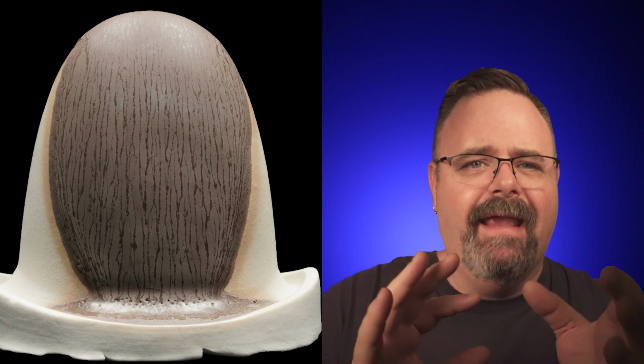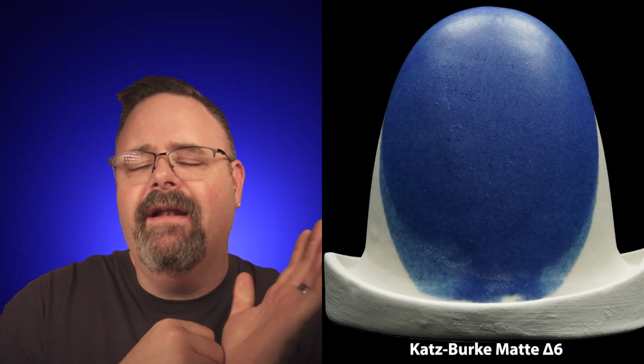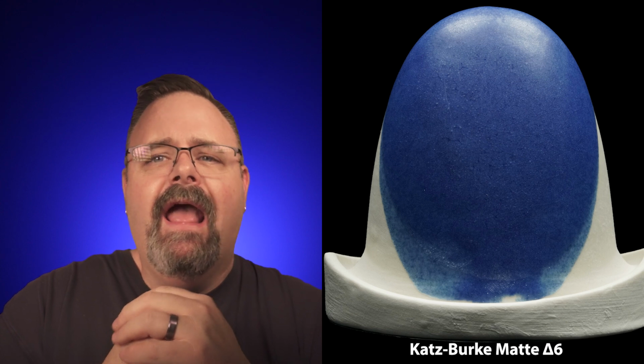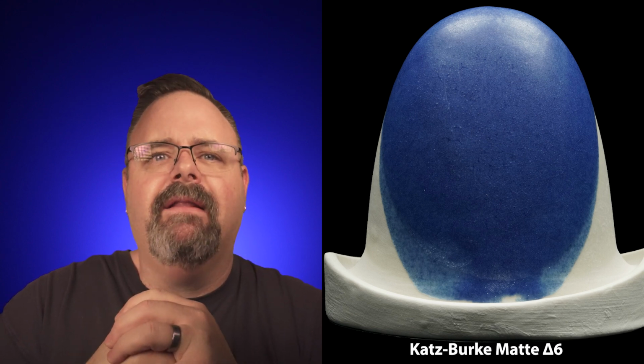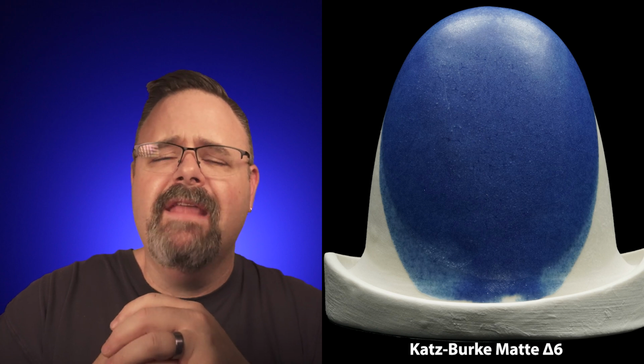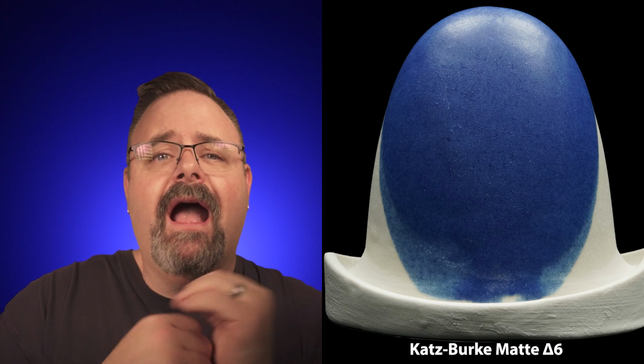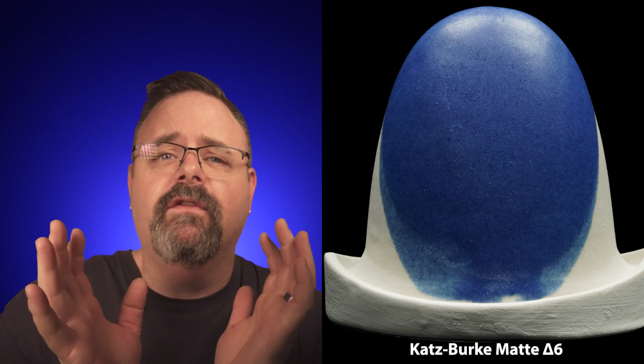So a matte glaze can run, but a matte glaze, more importantly, is not just matte because it's got underfired minerals in it. It's because it's growing crystals. But how can we identify that? This glaze is one of mine. It's very popular. You can find it on Glazy and all over the ceramics internet. And this is the Katz-Burke matte. This is a matte glaze at cone 6 I developed with my student Anna Burke many years ago. And this is a really robust, true matte glaze. And when I say it's a true matte glaze, I mean it's a glossy glaze that crystals grow inside of. And that's a really important distinction.